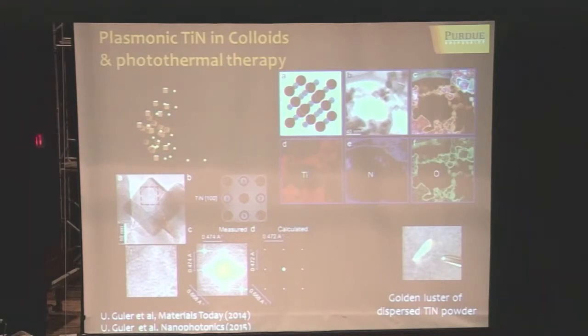You could see that they have single crystal quality as opposed to gold nanoshells, which are indeed polycrystal, as confirmed by this diffractogram. So very nice quality, and they're very cheap as opposed to gold.